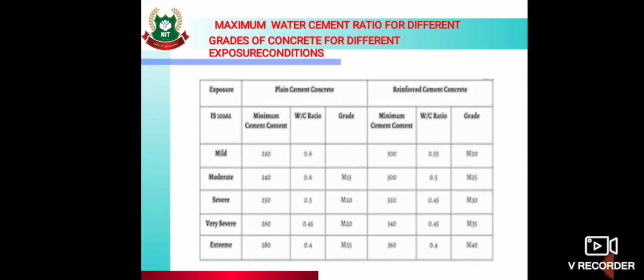So here this table shows the water cement ratio, minimum cement content, and minimum grade of concrete for different exposure conditions. For plain cement concrete, with mild exposure condition, minimum cement content required is 220 kg per meter cube, water cement ratio is 0.6. Then for moderate condition, 240 minimum cement content, water cement ratio 0.6, suitable grade is M15. Then for severe condition, minimum cement content 250 kg per meter cube, water cement ratio 0.50 and grade M20. Very severe condition, minimum cement content is 260 kg per meter cube, water cement ratio 0.45 and grade is M20. Then for extreme it is 280, water cement ratio 0.4 and grade is M25.